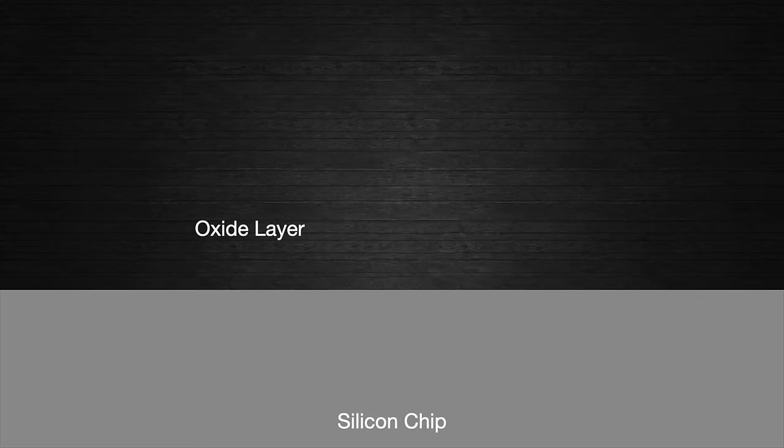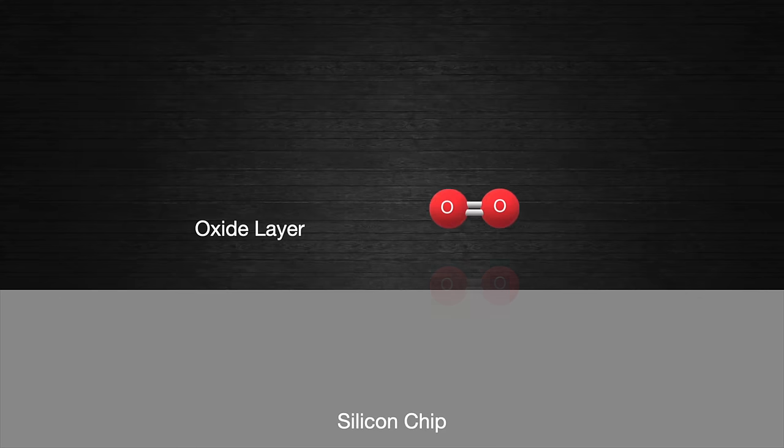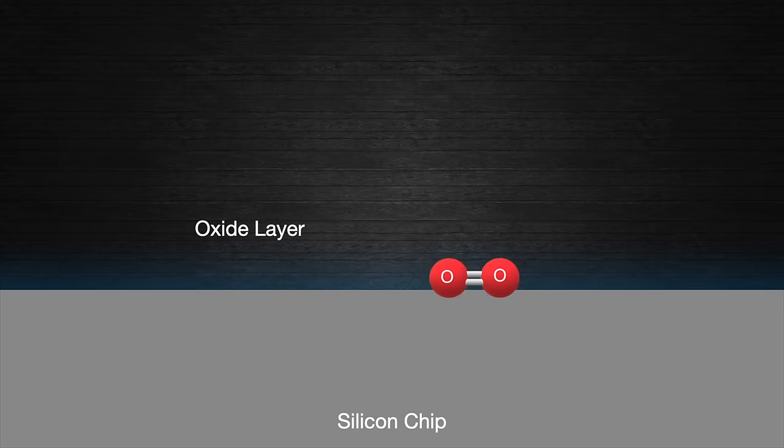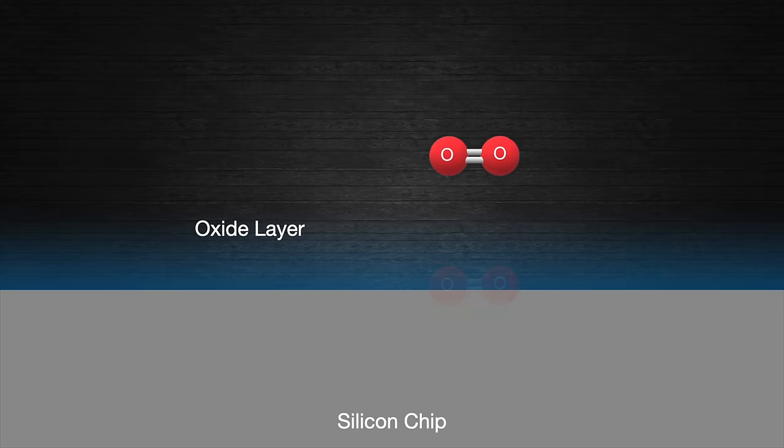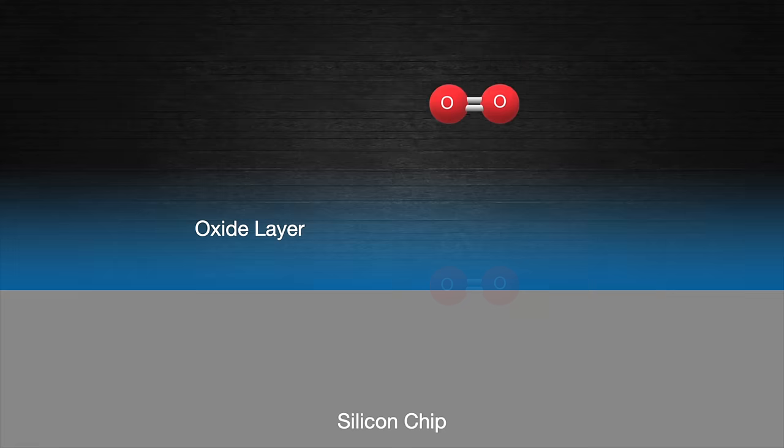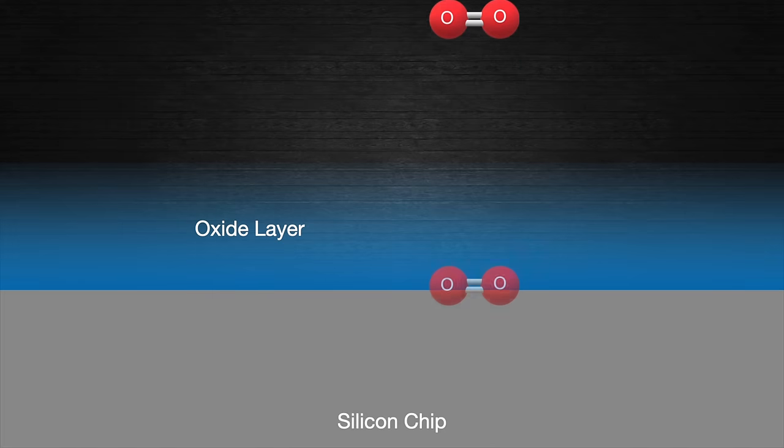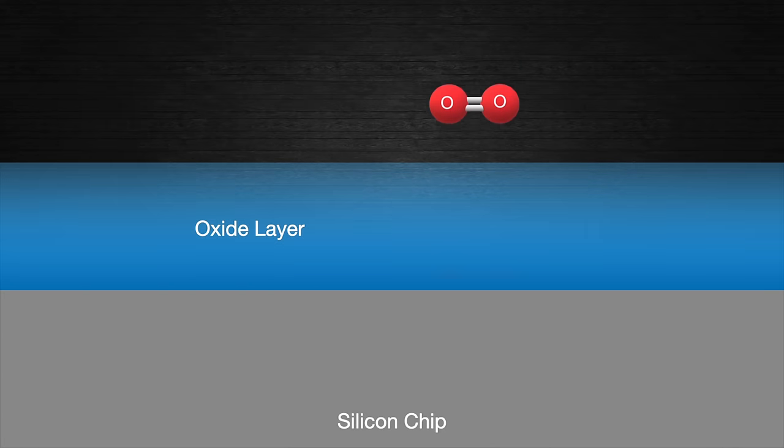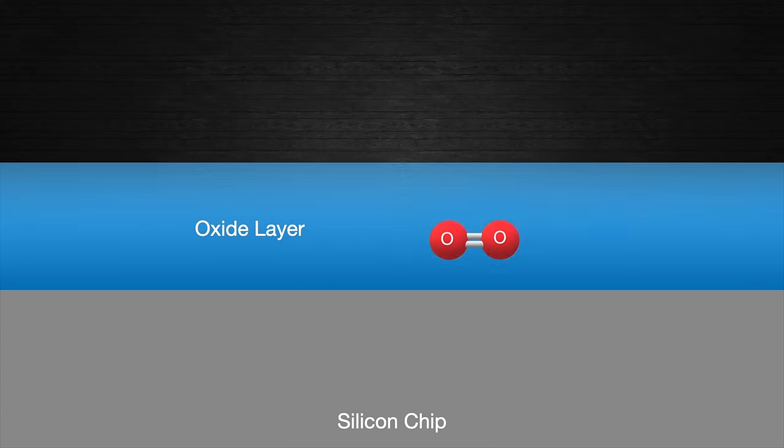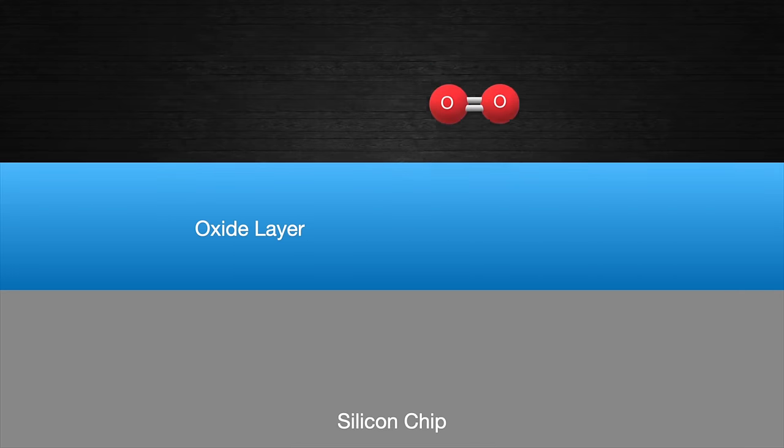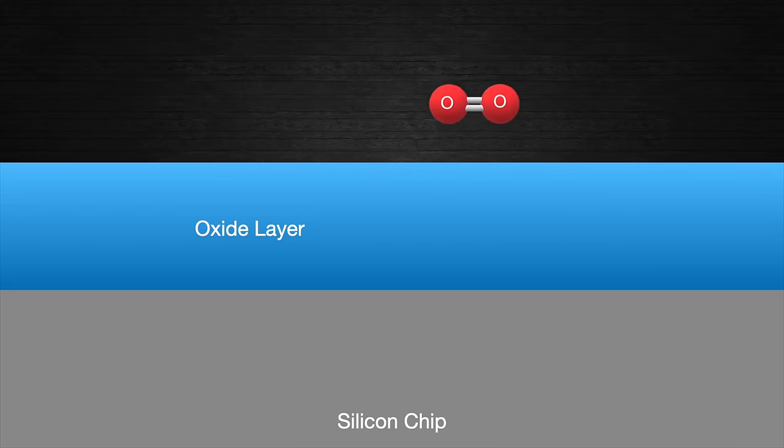Why is that? Well, the reason for this is simple. The reaction that creates the silicon dioxide is happening at the silicon surface, which is initially exposed, but slowly is being buried beneath an oxide layer. In order to create more oxide, new oxygen has to penetrate the entire thickness of this existing oxide layer, and then react with the silicon to form silicon dioxide. The thicker the oxide layer, the less oxygen reaches the surface, and the slower the layer will grow.